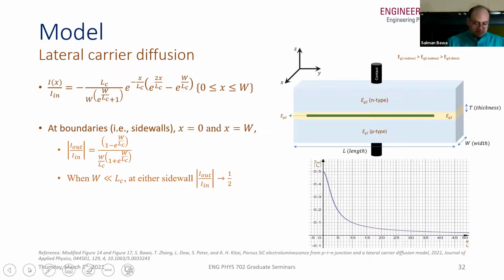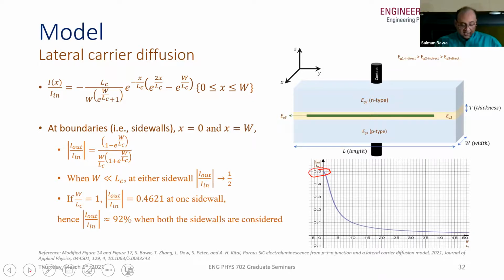And there are two things that we learn from this graph. One is that when the width of the device is much less than the carrier diffusion length, at either side wall, the ratio of the output diffusion current to the input current is approximately half. So it's reaching about half. Another thing is that if the width of the device is the same as the diffusion length, that is, the ratio is 1, then the ratio of the output current to the input current is about 92% on either side, on both side walls. So 92% of the carriers are being collected at the side walls if the width of the device is the same as the carrier diffusion length.